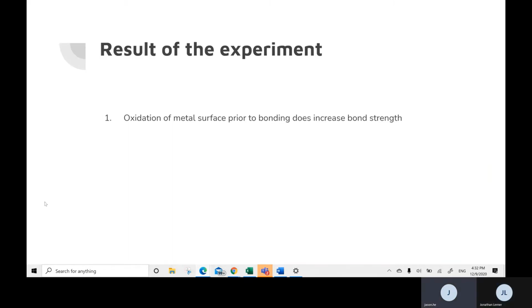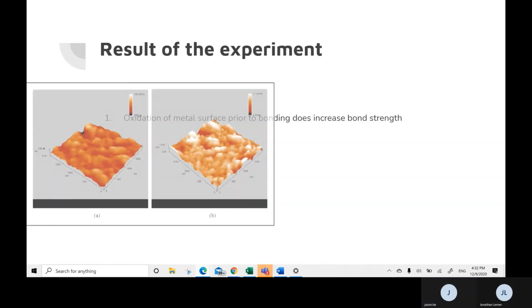So now I'm gonna talk about the result of the experiment. The first thing we need to prove is the oxidation of metal surface prior to bonding does increase its bonding strength. The two pictures on the slide shows the comparison between metal surface before and after oxidation. You can see some metal oxide formed on the surface of the metal, which will be proved to enhance the bonding strength of filler glass powder on the alloy.